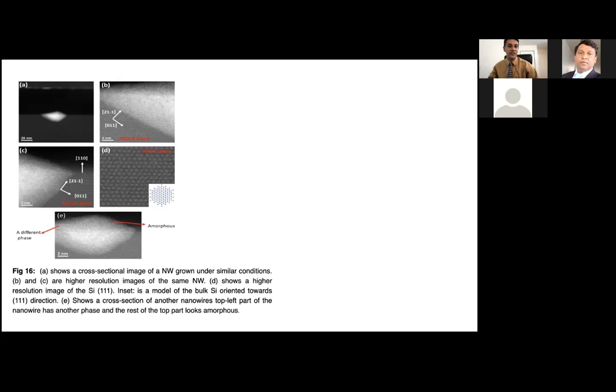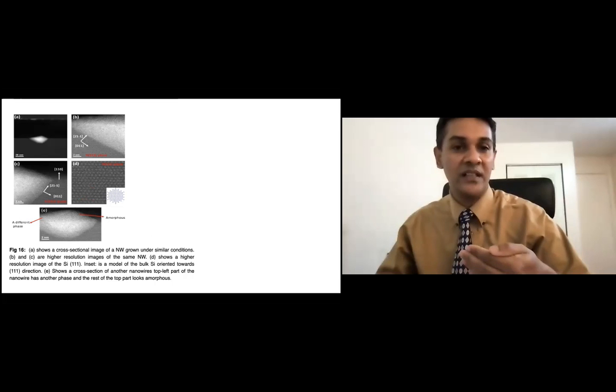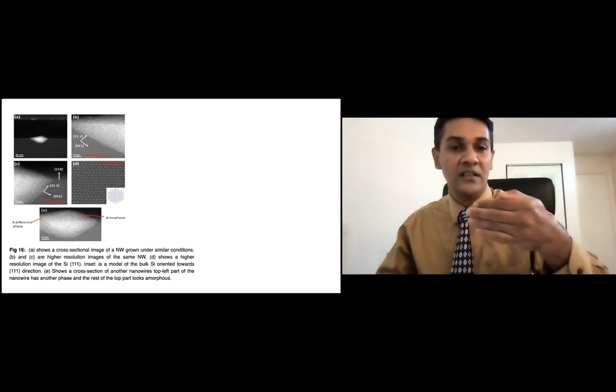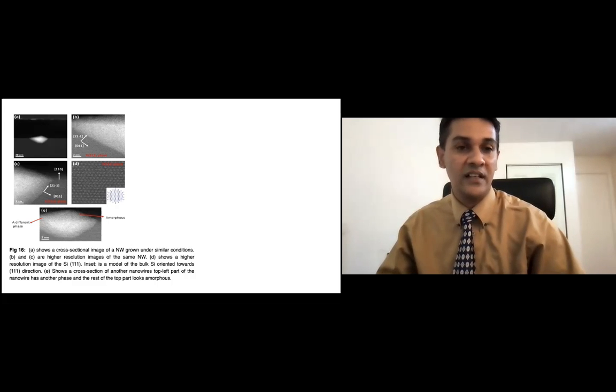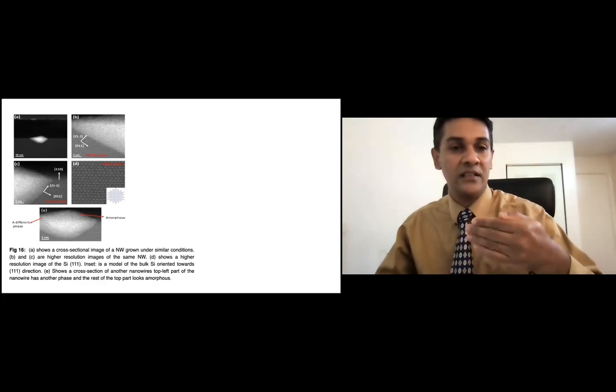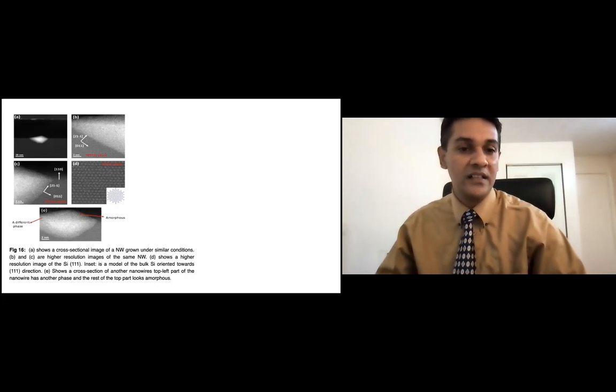So we got some high-resolution images. You can see these arrows show the high symmetry directions of the bulk silicon. This cut is perpendicular to the nanowire. You are looking at one plane, right? That is why you see this hexagon structure, because one plane has a hexagon structure. So we are looking at one plane, the perpendicular cut to the nanowires.